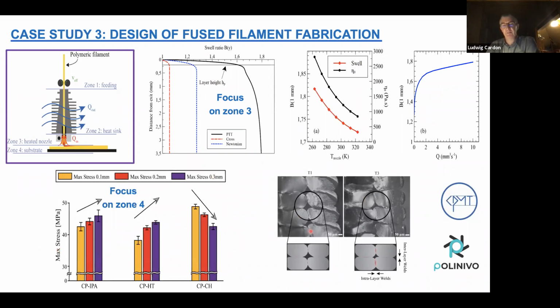And you see as example here in this case, we also look inside, depending on the flow behavior, depending on the deposition rate and the cooling system and the die swell. We want to investigate what we call the intra and interlayer adhesion of the filaments of the substrate you deposit. So, and then we try to play, let's say, instead of big gaps, you think it's a very big gap, but finally it's a small amount.